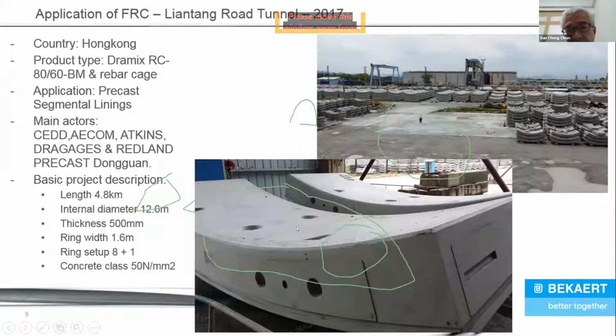This is use of fibers in the Liantang Road Tunnel project in 2017 in Hong Kong, built by Dragages and precasted in Redland Precast in Dongguan. And these are the thickest segments so far that are using fiber concrete combined with rebars. This is a hybrid segment. The thickness of the segment is 500 millimeter, but purely this is because of the diameter of the tunnel, which is 12.6 meter in diameter.